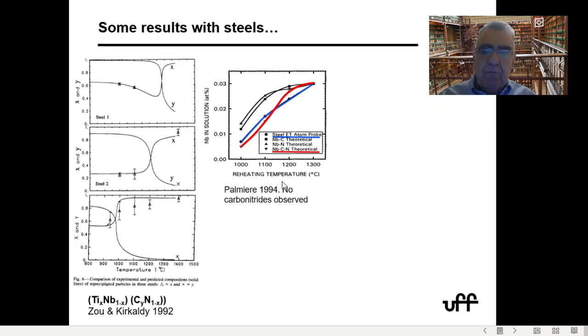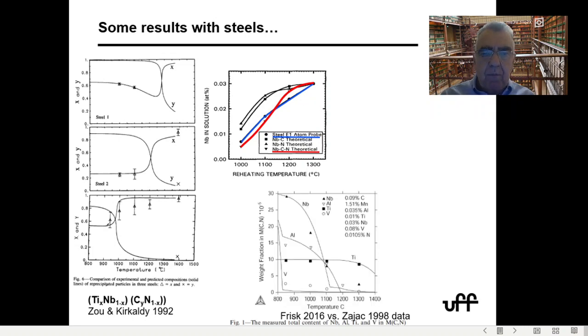Palmiere tried to simplify, and he did atom probe, he measured the composition of the steels and the solubility, but it's a little bit conflicting because he said there were no carbonitrides in his steel, but the best fitting for solubility was the carbonitride solubility product.